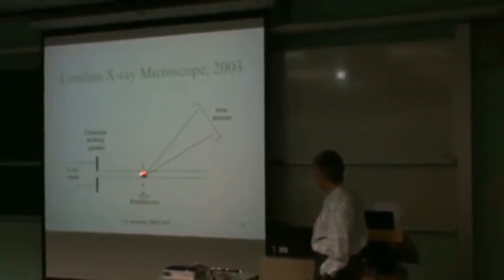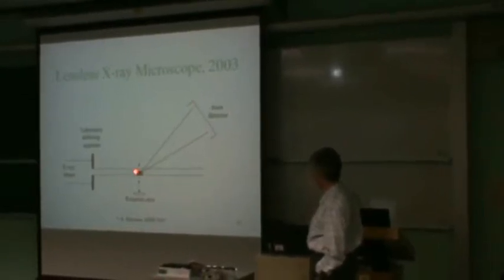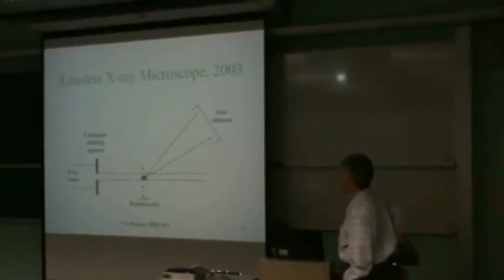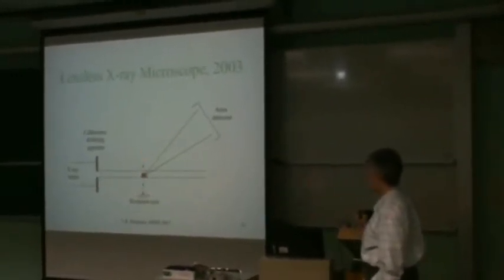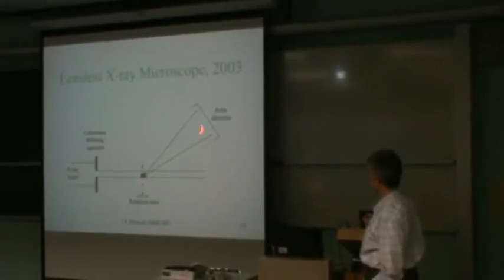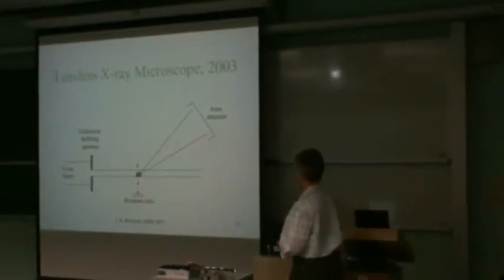We take out one coherent mode from the source, and we put it on the sample and measure the diffraction pattern. And because it's coherent, we see interference coming from all of the extremities of the sample. And if we rotate the sample, we get a full 3-dimensional diffraction pattern, which is giving us complete information about the 3-dimensional structure of the sample.